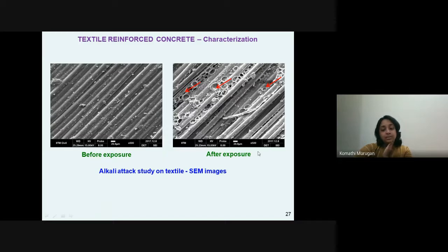What happens on exposure of these in the alkali solutions? It seems like the glass that is present in the fibers dissolves. So there may be a question: there is a coating on the fibers, so why is the glass going to dissolve? What we say is the coatings are done manually or mechanically on the textiles, so there tend to be certain holes or flaws in the coating as well. So whether the coating is present or not, the glass is essentially attacked by the alkali that is present in the system.